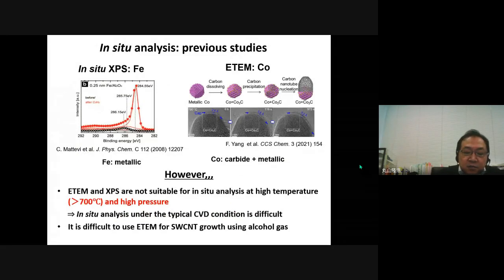So far, several studies about in situ analysis for carbon nanotube growth have been reported using TEM and XPS. However, basically, TEM and XPS are analysis techniques under high vacuum. Therefore, they are not suitable for in situ analysis under the typical growth condition in CVD. Also, it is difficult to use TEM for observation of nanotube growth with ethanol gas.